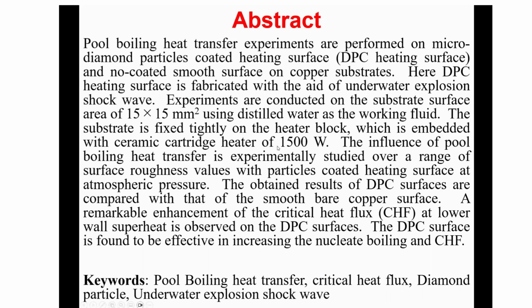The substrate is fixed on the heating block, which is embedded with a ceramic cartridge heater of 1,500 watt. The influence on the pool boiling heat transfer experiment is the study of the range of the surface roughness values of the particle coated heating surface at atmospheric pressure. The obtained result of the DPC surface is compared with that of the smooth bare copper surface. A remarkable enhancement of critical heat flux (CHF) at the lower superheat is observed on the DPC surface. The DPC surface is found to be effective in increasing the nucleate boiling CHF.